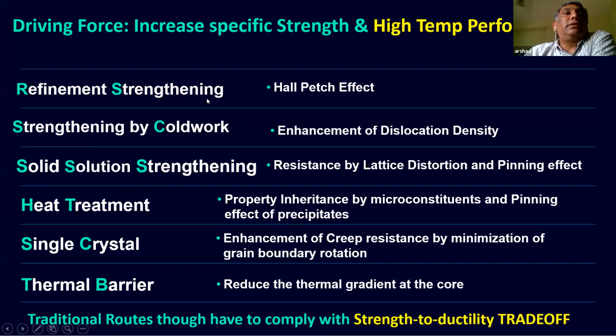The first one is grain refinement strengthening, of course the Hall-Petch relationship. Second, strengthening by cold work, through dislocation density. Then solid solution strengthening, that is the resistance by lattice distortion and pinning effect. In a solid solution, the foreign atom going into the alloy will be either larger or smaller than the parent solvent atom, so it will replace it. If it is so small that it can be housed in the interstice, then it will be an interstitial solid solution. In all three possible cases, the distortion in the lattice affects dislocation movement, and hence it strengthens. The next is heat treatment. These are the four basic conventional routes for strengthening. Number one, refinement. Number two, cold work. Number three, solid solution. Number four, heat treatment.